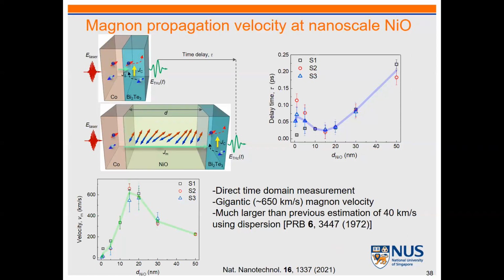Okay, so the next question was, what is the propagation velocity of this magnon inside nickel oxide? Because this terahertz measurement is basically a time-resolved measurement, you can record its physical time. So as a function of nickel oxide, we can measure when there is no nickel oxide, what is the emitted time, versus when we insert nickel oxide, what is the emitted time. Then we just look at the time difference, then divide by nickel oxide thickness. So basically that will give a rough estimation.